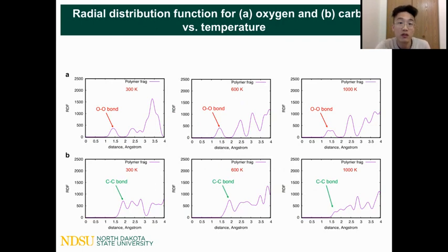We further investigated the radial distribution function for different types of atoms over a wide range of temperature. The RDF here describes how the density varies as a function of distance from a reference particle. Actually, there's no big difference at lower temperature. However, if you look at the red figures, the figures on the right side, the peaks become broader, both for oxygen to oxygen and carbon to carbon bonds, which indicates an increasing degree of amorphization. Moreover, the intensity at high temperature is much lower than at lower temperature. I feel like probably due to some breaking of bonds, because at high temperature the CNC is kind of in a melting state.